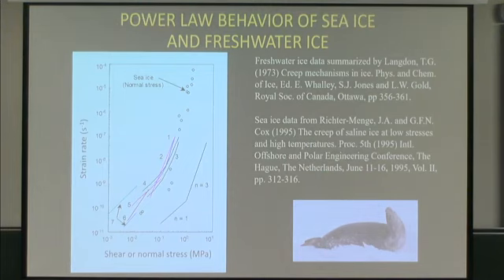So this is an accumulation of strain rate versus stress, shear or normal, published actually quite some time ago, but it was kind of a nice compilation. You see this follow-up, this n equals 3 is what's typically used for ice. Sometimes it extends to low stresses, sometimes not. And according to my analysis and a reasonable amount of my data, that's due to a threshold level of dislocations, the initial level. Jackie Richter-Menge had some nice creep data that I stuck in here that actually shows the fall-off from n equals 3 at low stresses. I see that in my experiments as well. This just was a nice compilation.